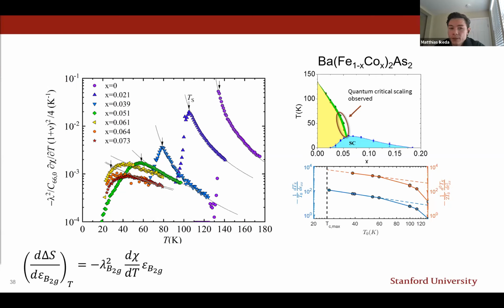We have thought a little bit about this. It would be really interesting to measure the elastocaloric effect at really low temperatures, maybe in a dilution refrigerator. What we would measure is strain-tuned Grüneisen ratios, but since we apply different strain components, we'd actually measure various Grüneisen ratios, namely symmetry-conserving and symmetry-breaking Grüneisen ratios. And it would be really interesting to study whether one of these Grüneisen ratios might diverge at low temperatures. But presumably it is the B2g Grüneisen ratio which should diverge.